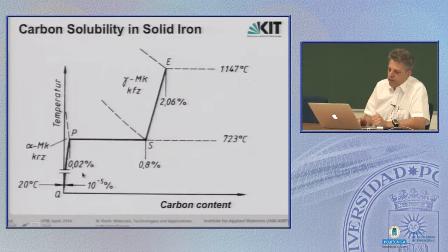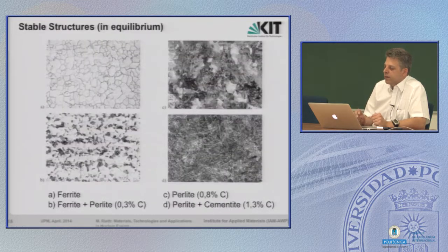This is a magnification of exactly this edge in the iron carbon system. Again, 0.02% is the solubility limit in alpha iron, and 2% is the solubility limit in gamma iron. This is how the steel looks. Ferrite has these, let's say, more round shaped grains. That's typical for ferrite iron. If the carbon content is increased, then we have a mix of ferrite and perlite. That's an example of 0.3% carbon. The white ones, this is ferrite. The dark ones, this is the perlite, the eutectoid phase.